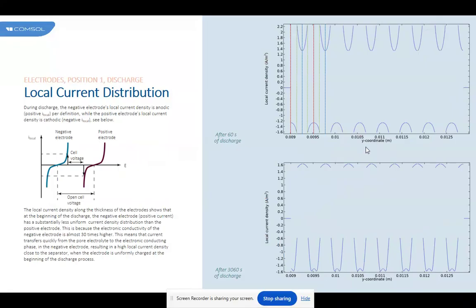Local current distribution. During discharge, the negative electrode's local current density is anodic, positive by definition, while the positive electrode's local current density is cathodic, negative, I local. The local current density along the thickness of the electrodes shows that at the beginning of the discharge, the negative electrode, positive current, has a substantially less uniform current density distribution than the positive electrode.